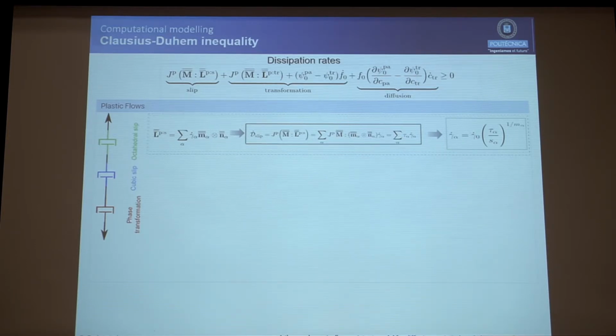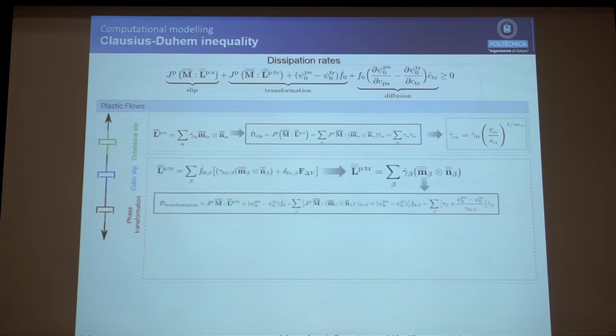But this becomes more interesting for the transformation, because for the transformation, the velocity gradient can be a compound of a shear strain plus a volumetric change. But in terms of microtwinning, we don't have volumetric change, so we will have just the shear strain. If we include that into the term for the dissipation rate of the transformation, we get to this driving force here, multiplying the plastic multiplier for phase transformation.